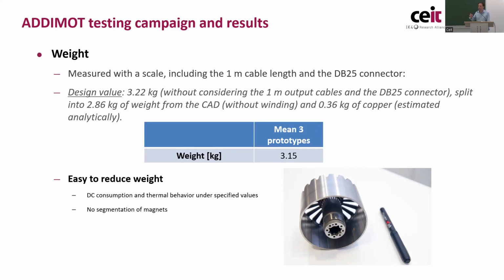So we could reduce, for example, from 55 millimeter to 44 millimeter the active length of the motor. But from 44 to 33 millimeter, which is a great reduction of weight, we couldn't do it because the DC consumption was above 150 watts. But for a second round or second design, it would be very easy to use block magnets, not segmented, and to reduce, for example, 3-4 millimeter the length. We will be well under the 150 watts of consumption, and this 150 grams in excess that we have, we could reduce it.